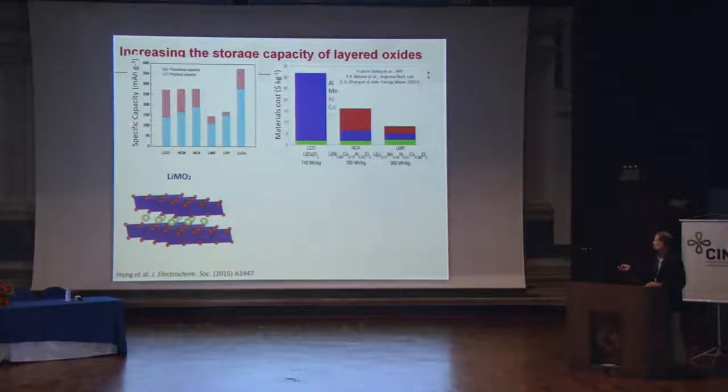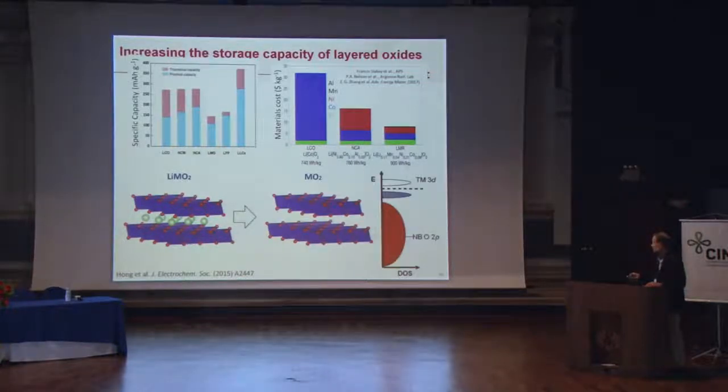So the reason that we are not able to extract the complete theoretical capacity out of these is illustrated down here. This is the layered structure that's typically found in the metal oxide cathodes. In green, I'm showing you the lithium ions. They basically form a layer. The red is the oxygen, and you can't really see it, but the transition metals, which are coordinated to the oxygens, are shown in the blue layers that sit in here. What happens when we charge the battery is the lithium is extracted from the cathode and goes to the anode. The lithium that was in this layer is now taken out, leaving the structure to look like this. The oxygens are, of course, negatively charged.